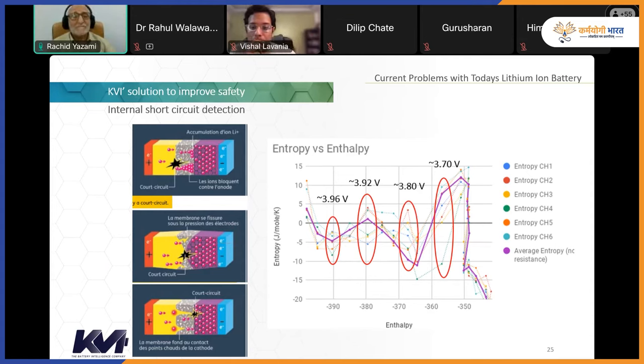So in a battery pack, there is a BMS, a battery management system, and among the data that the system is collecting is the temperature. Now, the problem with the internal short circuit at the early stage is that even though we have a local heat, what we call the hot spot, this hot spot is not powerful enough to influence the overall temperature of the cell. So we cannot detect an early stage of internal short circuits only by measuring temperature.